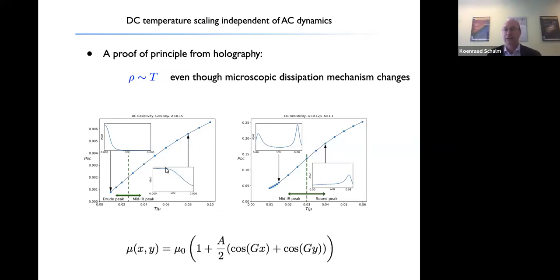Okay, there could still be momentum relaxation dominating the resistivity, but it does so in a very, very different way than before. And you can even go further: in a slightly different model, I can have a system with a regime where I have a linear resistivity. Here I start with a regime where this peak on the left in the optical conductivity is this same peak here, and there's a second peak at much higher frequency. If you go to higher temperature, these two peaks collide and are left with one large, big, fat peak at high frequency, even though throughout this regime, the essential temperature scaling of the resistivity doesn't change.